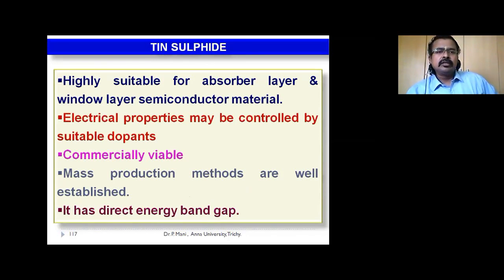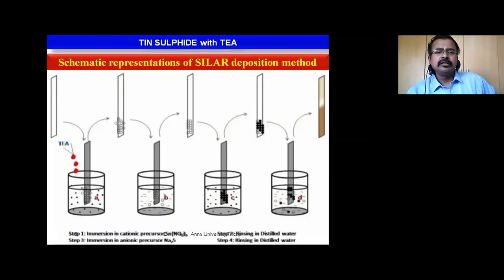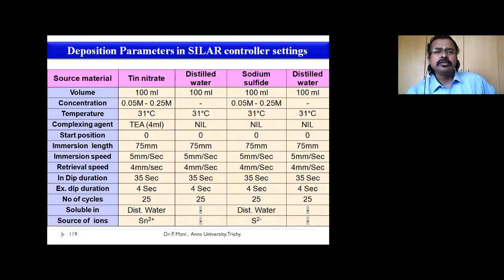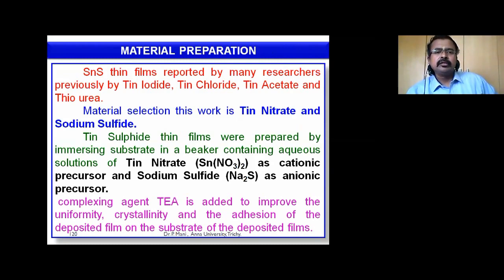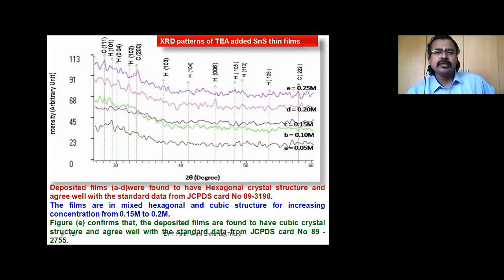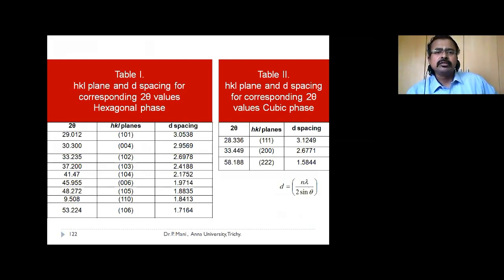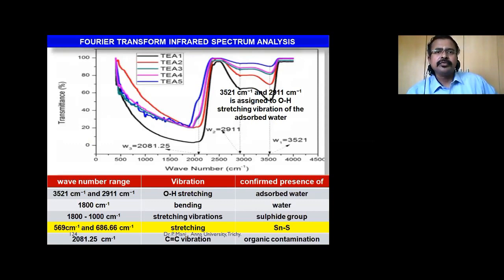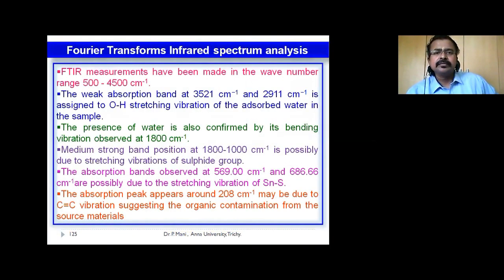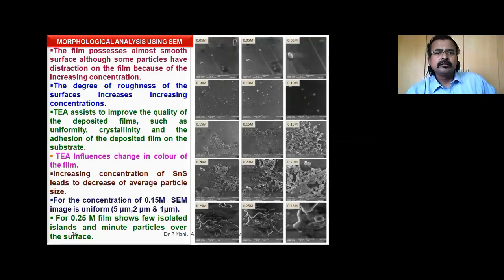So, as in the earlier method, we are coating tin sulfide. These are the deposition parameters. We are preparing like this. XRD patterns are coming like this, showing the materials. We are doing the calculations. FTIR is showing different vibrations, wave number range. It confirms the presence of adsorbed water, sulfide group, tin sulfide, organic contamination, etc. Then it is showing the uniform coating and structures.